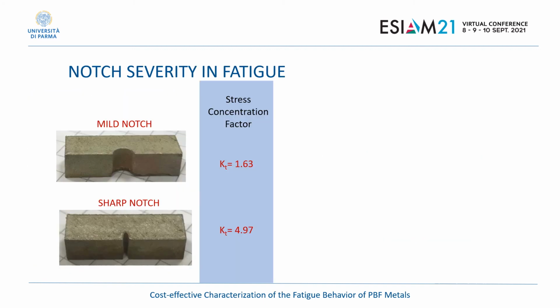We also investigated notch severity in fatigue. Therefore, we consider the mild notch geometry that we already tested, and we also prepared specimens with a sharp notch in them. The sharp notch achieves a stress concentration factor of about 5, which is significantly larger than the mild notch stress concentration factor of 1.6.